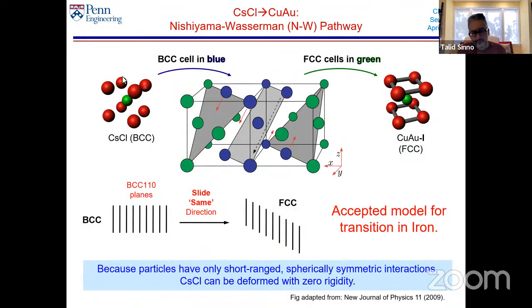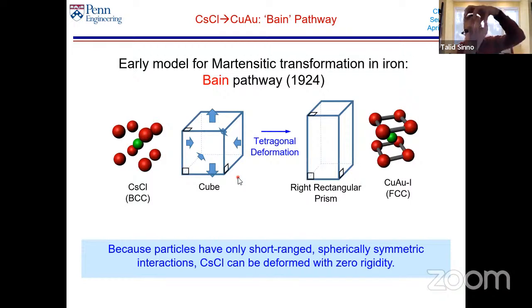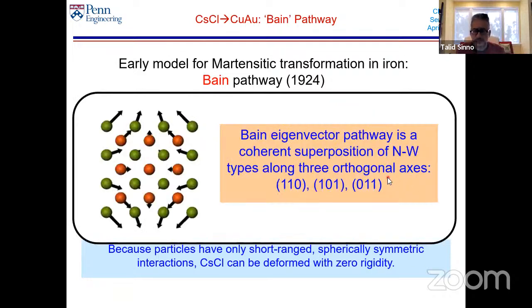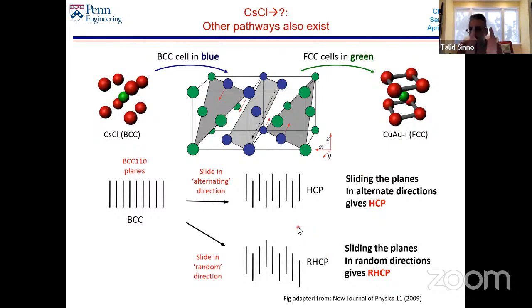So just to give you an idea, this is cesium chloride, which is the BCC configuration. If you take the 110 planes in BCC and you just shear them, you go to FCC. That's a very simple pathway. And this is a well-established martensitic transformation pathway, the Nishiyama-Wasserman pathway. If you do a uniaxial stretch, and then compression in the other two directions, this is called the well-known Bain pathway, also goes from BCC to FCC. And then there are other pathways. I'm going to skip this. There are other pathways that if you take each plane and you slide them up and down in an alternating fashion, you go from BCC not to FCC, but you go to HCP. Okay, so it's another ordered phase. It's still close packed, and it's degenerate energetically with copper gold.